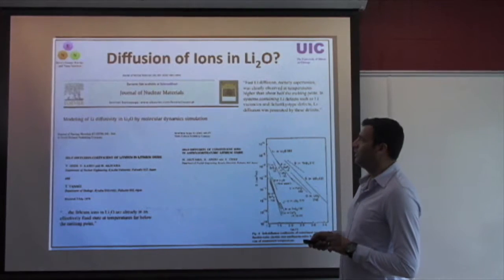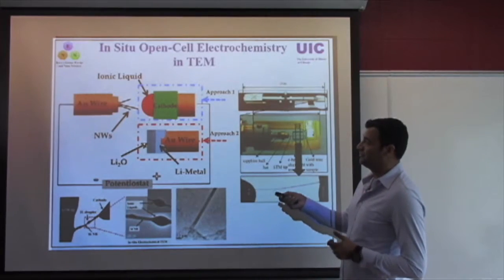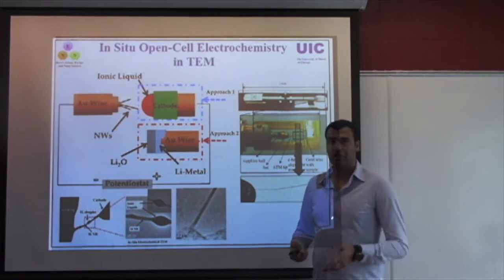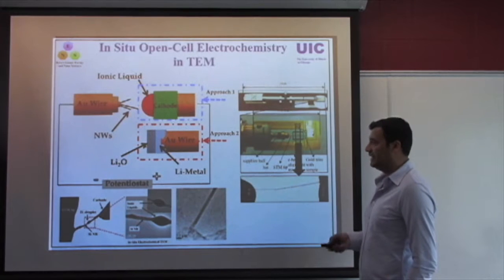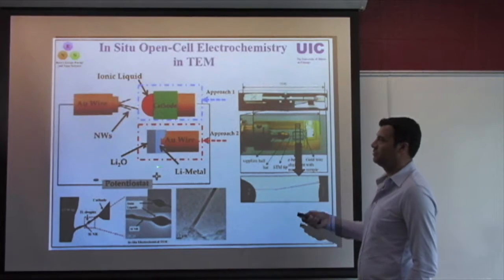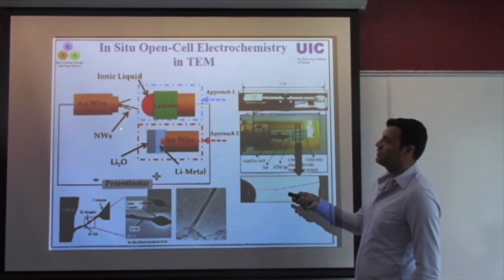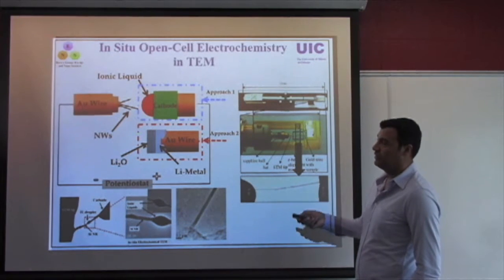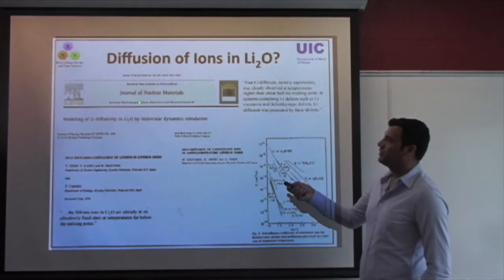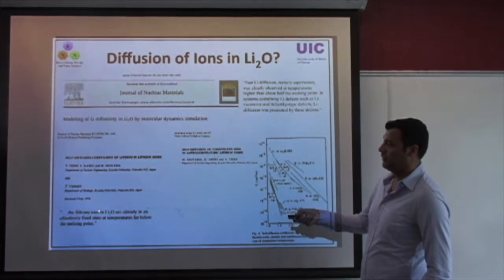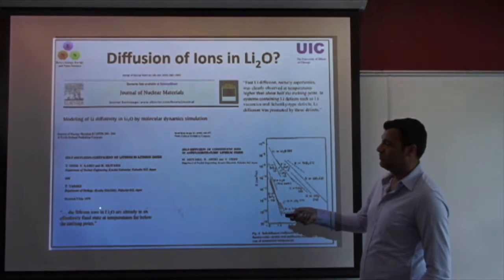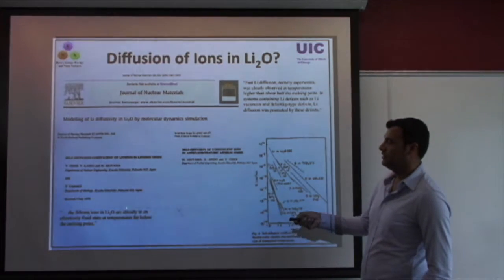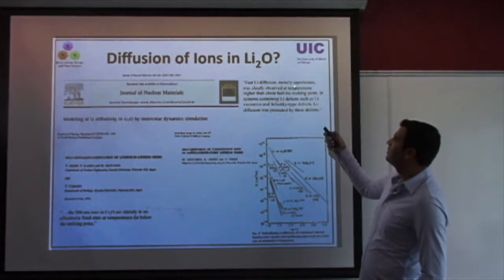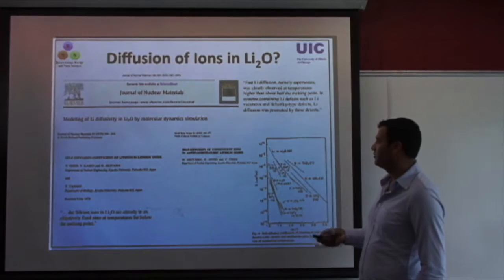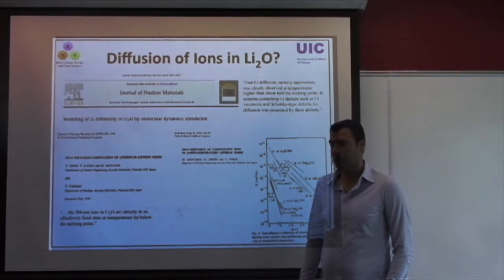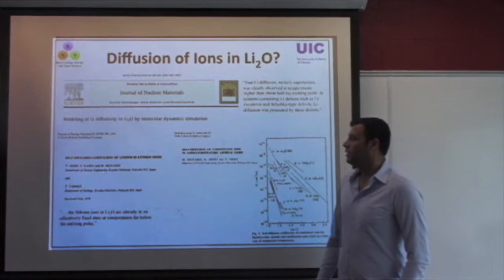Something I should mention is that there is an interesting concept going on here that could be a subject of more in-depth studies by the electrochemists, especially how the transport of the ions from lithium through this lithium oxide happens. If you look into the literature, there are several works that have shown that lithium can have a very fast transport in Li2O. I've summarized some of the examples here that people have reported very fast diffusion of lithium in Li2O, and that's what we see when we do experiments.